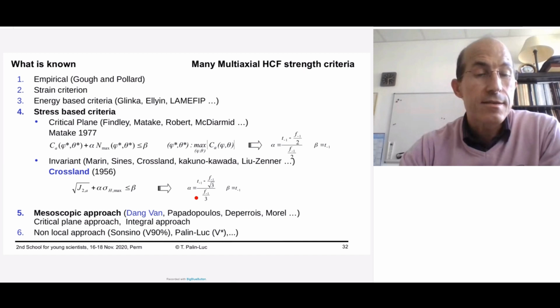In literature, as I said, there are many criteria: empirical ones, strain-based criteria, energy-based criteria, and stress-based, and macroscopic ones, and mesoscopic ones. I'm presenting you today only criteria based on a stress-based approach, and there are critical planes at the macro scale and critical planes at the meso scale. Consequently, I'm presenting you one approach which is at the macroscopic scale, which is named the Crossland approach, which is a linear combination of the hydrostatic stress and the amplitude of the deviatoric invariant.